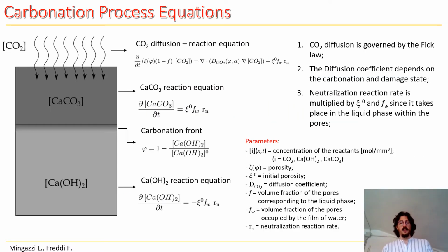The model for the carbonation process is based on the standard diffusion-reaction equation system. In particular, for the carbon dioxide, the diffusion part is governed by Fick's law, with a diffusion coefficient which depends on the carbonation and the damage state of the material. The first one accounts for the change in porosity, and the second one accounts for the fact that CO2 can freely move through the cracks in the material.